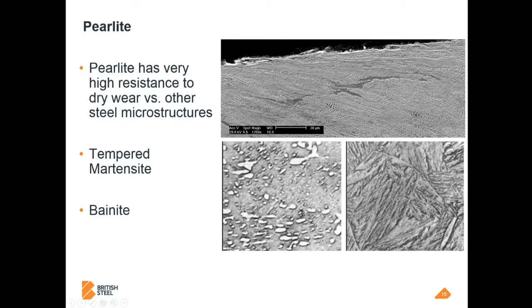But it work hardens to an incredibly high level, and that gives you this increased wear resistance at the surface, which is why pearlite has such good wear performance compared to other microstructures such as tempered martensite. So you can maybe get a tempered martensite structure with a 400 Brinell hardness, but under the surface, at the end of the day, it's a ferrite matrix with cementite spheres distributed widely throughout it, and they spall out at the surface and don't add much strength. And you're really just working on the properties of the ferrite.